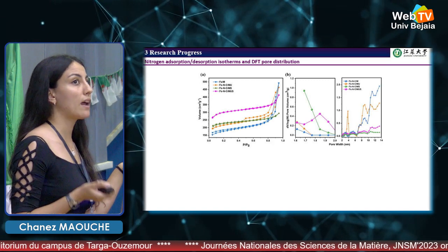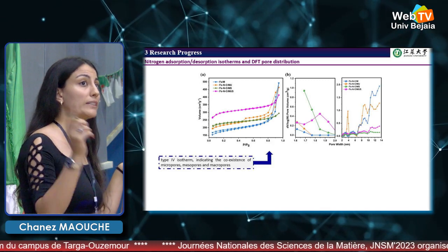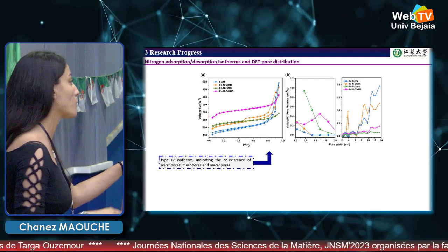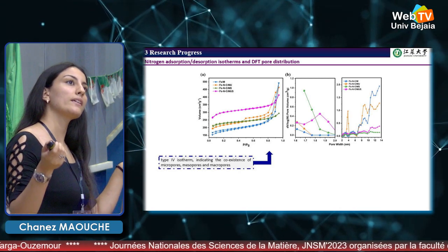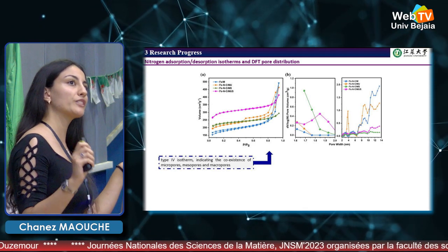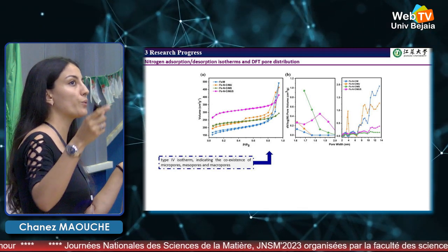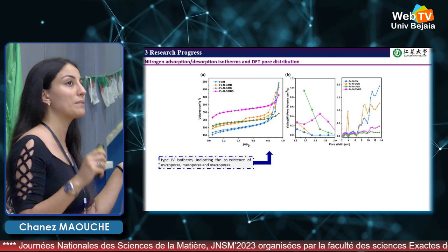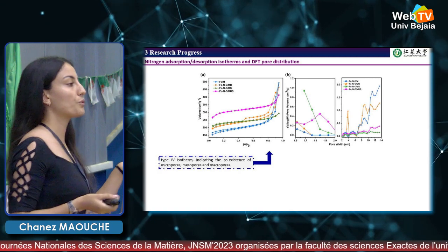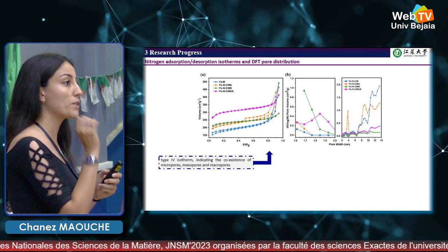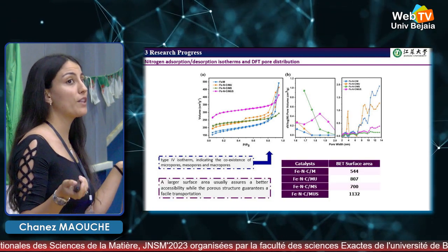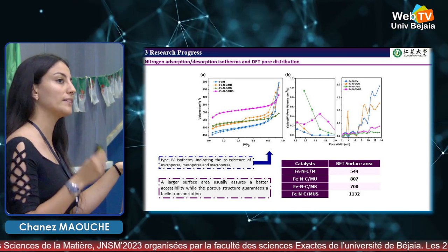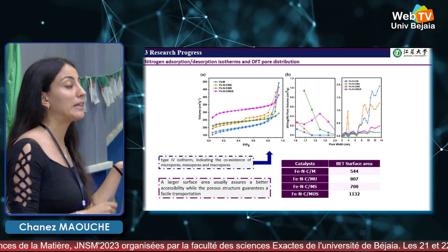The BET surface area was investigated, and the isotherm here showed the coexistence of micropores and mesopores. We can see, for the MS, that the introduction of sulfur led to the increase of micropores, while the addition of undecyl imidazole led to the formation of narrow mesopores. As well, the larger surface area shows that the addition of both ligand and sulfur led to an increase in surface area exceeding 1100.